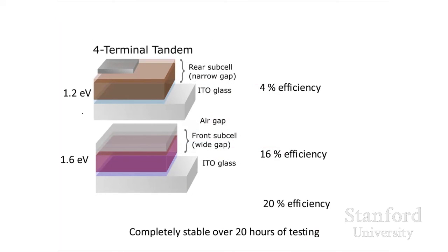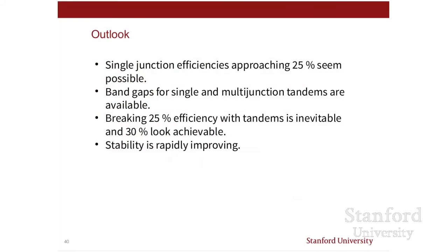We also made a four-terminal tandem with the low band gap material, and right now we're at about 20% efficiency. And it's very new material. We haven't been able to do full stability testing, but it was completely stable over 20 hours of testing under one sun. So I think the outlook for efficiency and stability is wonderful. You've seen how the single junction efficiency rapidly rose to 22. I'd be very surprised if it's saturated there. I'm optimistic that single junction cells might go to 25, and that the tandems will go up over 30% efficiency.